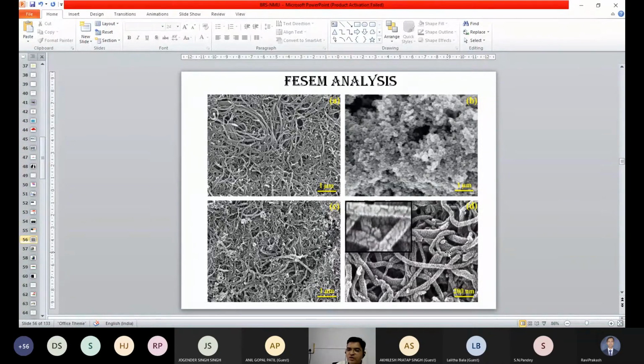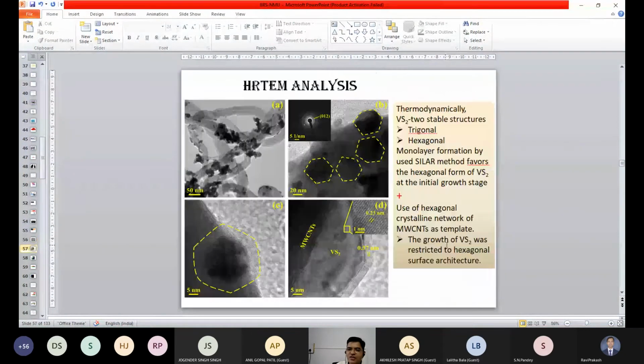But I told you that this vanadium sulfide has a hexagonal shape, and in the SEM analysis with the scale bar of 200 nanometer, it is not possible to see this. So in the next image, you can get an idea from this HRTEM analysis. This is the carbon nanotube, and these are the particles on the carbon nanotube. In image B, the darker things are vanadium sulfide, and it has a hexagonal shape. In image C, you can see exactly the hexagonal shape on the carbon nanotube, and here is the interface between the carbon nanotube and the vanadium sulfide.